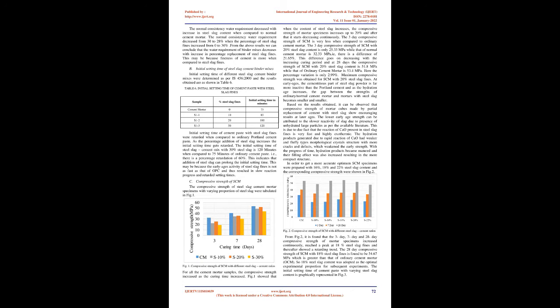The chemical activators of sodium sulfate, sodium silicate, sodium carbonate and sodium hydroxide with a dosage of 6% were used to activate SCM. Then, the initial setting time and compressive strength at the end of 3, 7, and 28 days of curing were measured. The chemical activator with the best activation effect was then selected. E. Determination of optimum percentage of alkali activator. In order to further study the effect of dosage of the selected alkali activator on SCM, steel slag cement mortar specimens were prepared by the addition of the best alkali activator found from the above step in the percentages shown in Table 4. The compressive strength of SCM was measured at 3, 7, and 28 days of curing to determine the optimal amount of alkali activator.